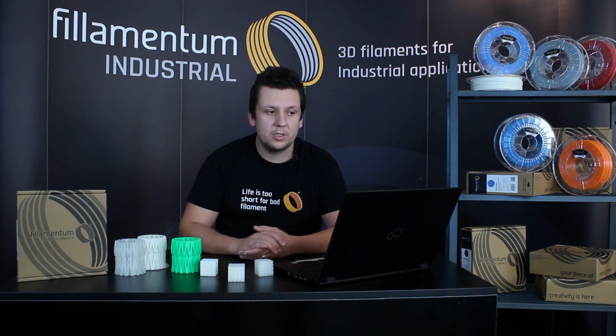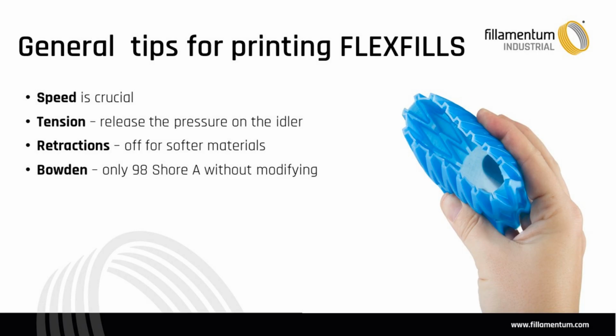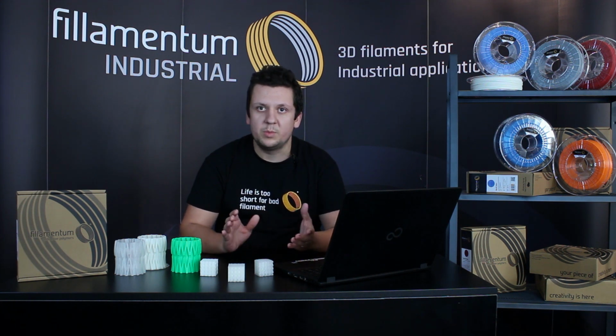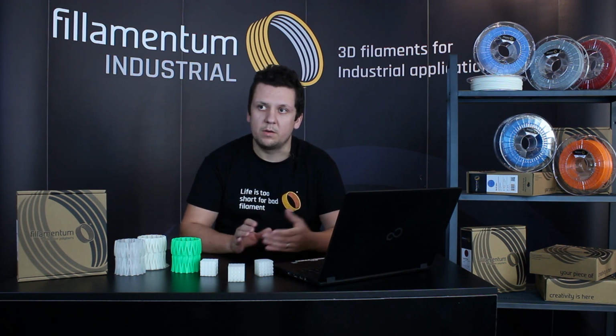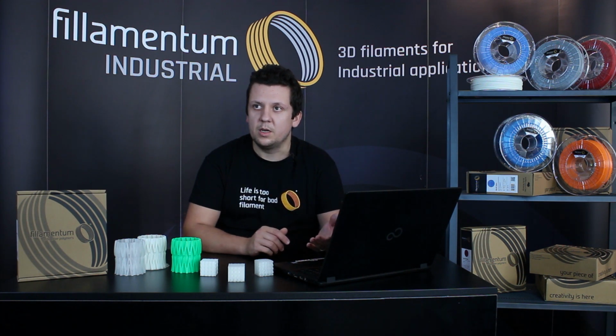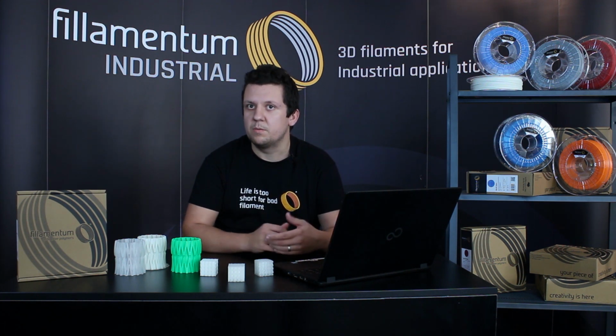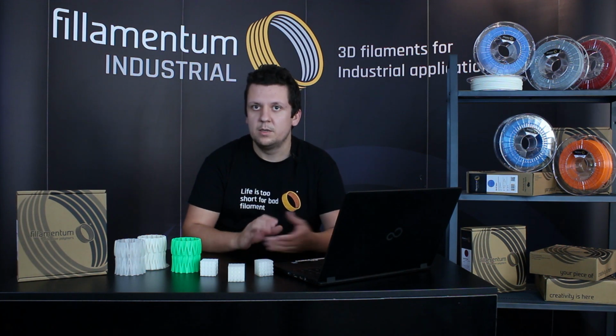So let's take a look at the general tips for printing with Flex Fills. For me, there are three main ones: speed, retraction, and tension on the idler. The speed is crucial when you're printing with flexibles. Generally 20 to 30 millimeters per second is the optimum value. Also, of course, it depends on the extruder you have. If you have an extruder which is designed for printing flexibles, you can run faster.